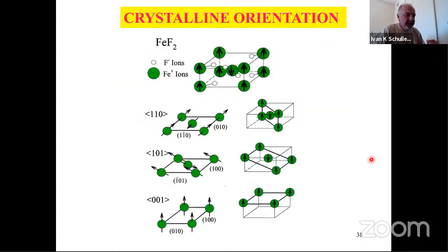So here is the big surprise. Okay, so here it is, the surprise. As I told you, a very comprehensive study. We can do 110, 101, and 001. Notice, the 110 surface, which I showed you before, is a fully magnetically compensated surface. It has as many spins pointing into the board as pointing out of the board, so it's zero magnetic moment. The 001 surface is fully uncompensated. It has lots of moments, all the moments are pointing in one direction.